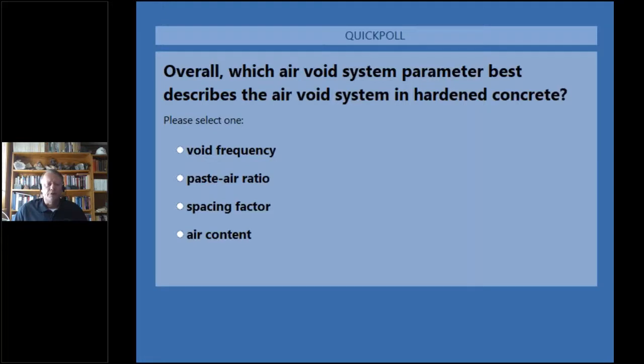Sounds good. Okay, so basically, I was just showing some images that there are a lot of factors that dictate the amount of air that occurs in concrete, not just the addition of admixtures or surfactants or how it's placed. There are other factors as well, including the alkali content of the cement, the use of water reducers, the aggregate particles we talked about already. The bigger the aggregates tend to decrease the amount of air in the mix. Total sand to total aggregate ratio, water cement ratio. I'll just list a few more.